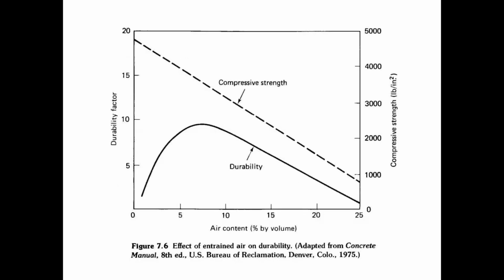All right, so let's talk a little bit about how air entrainment affects the compressive strength and the durability of the concrete. So shown here is a graph that illustrates how air entrainment helps to improve the durability of the concrete, helps to improve the freeze-thaw resistance of the concrete. But notice that that improvement in durability does have a peak. At around 7% air content, you get a peak in durability, and if you keep increasing air content beyond that point, then you actually get a loss in durability. All right, so we get a peak in durability using air content of around 7%.